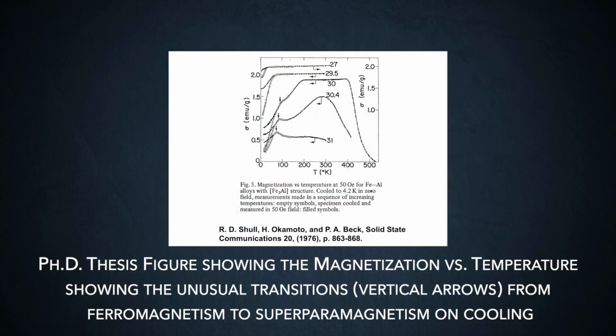And in fact, what we found in this particular system is that the material changed from ferromagnetic or long-range order to this clustered magnetic state, or perhaps more people called it not Mictomagnetic, but spin glass magnetic state at low temperatures, or paramagnetic at lower temperatures. So this is very unusual, of course. All ferromagnets become paramagnetic as you go up in temperature. Here was this material which went paramagnetic from ferromagnetic state as you cooled it below room temperature. So we coined this term, this inverse Curie temperature in this one particular alloy.